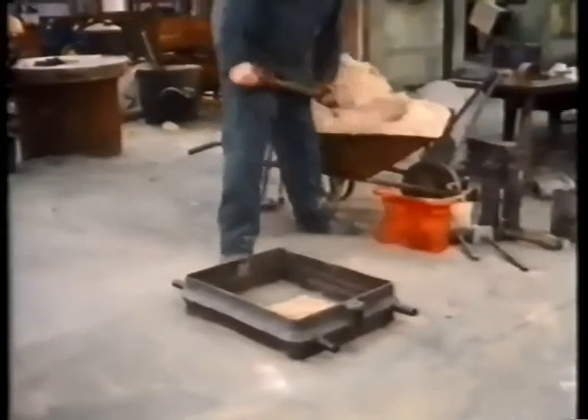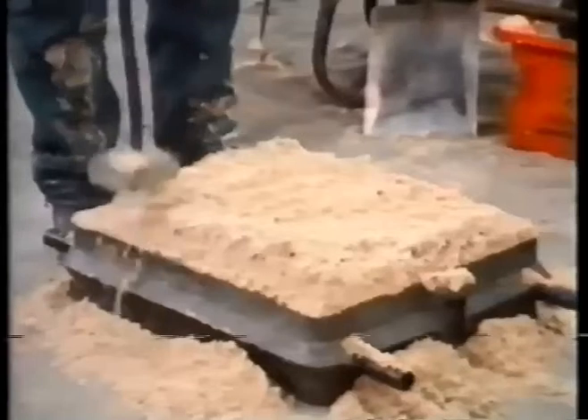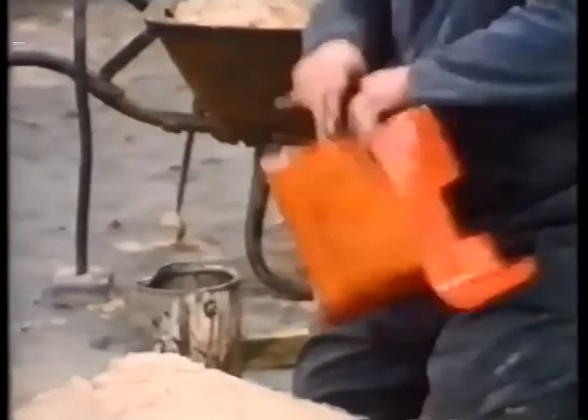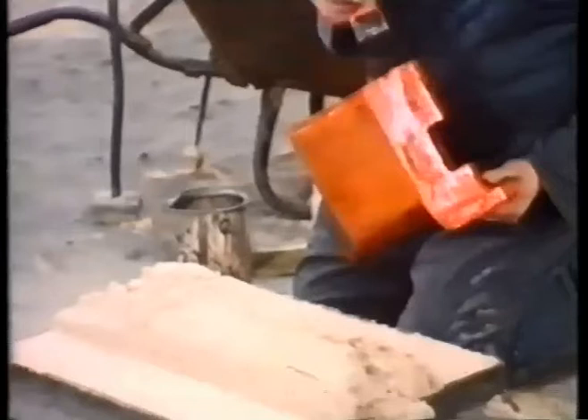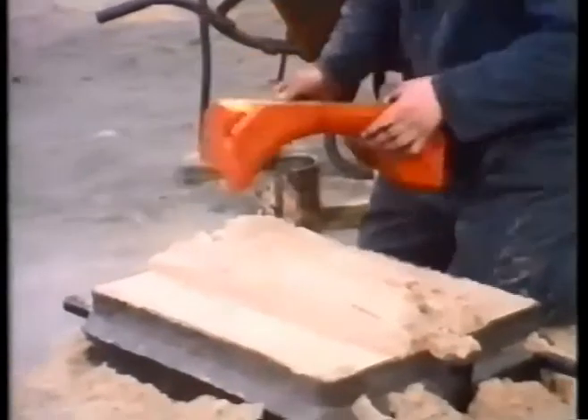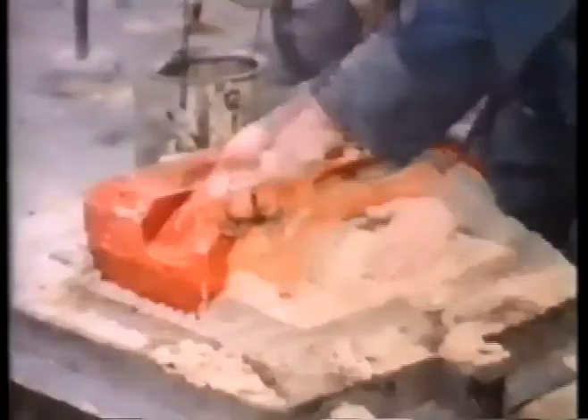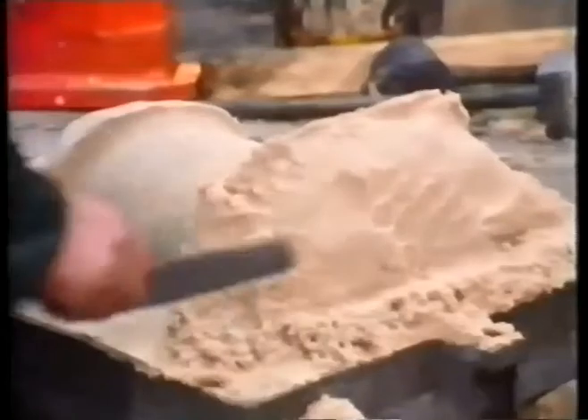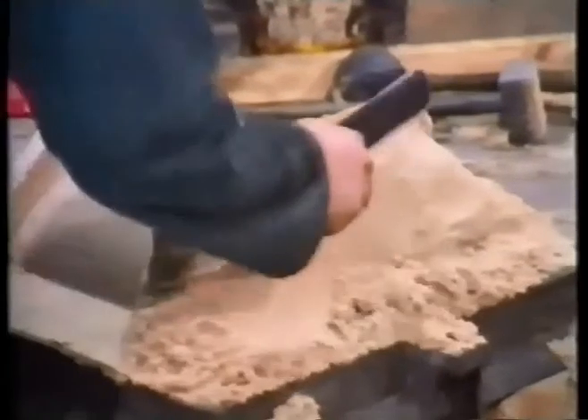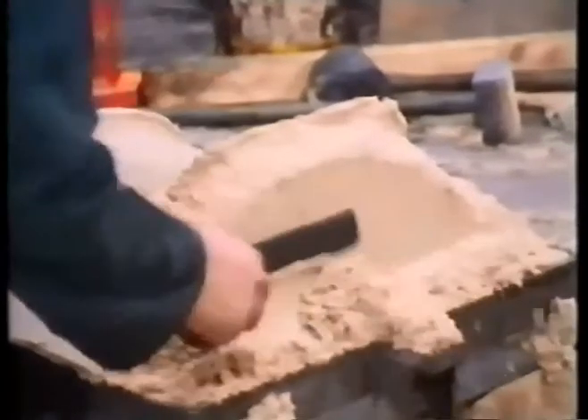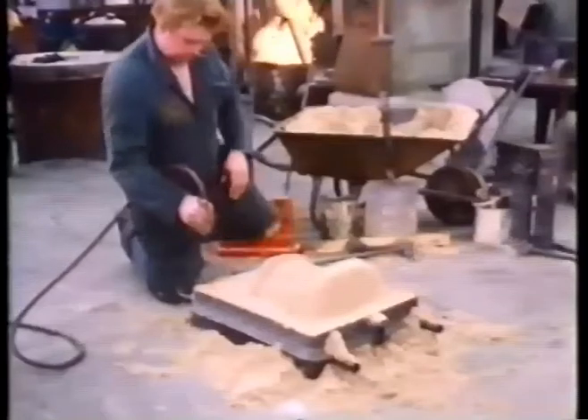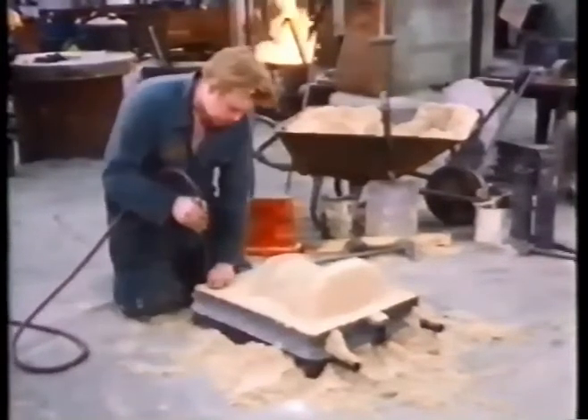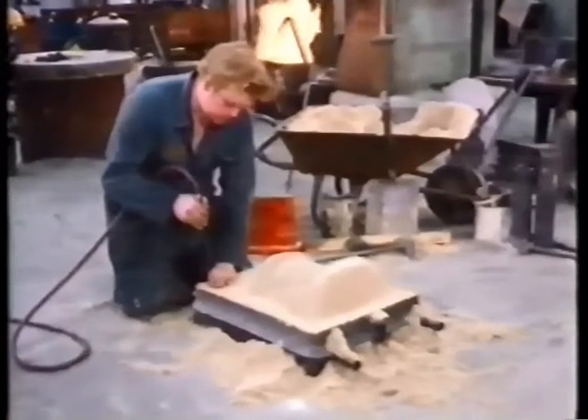First, a mould box is filled with a suitable foundry sand, which is tamped down to ensure that it fills the box properly. Then a wooden pattern of the shape of the bearing we require is placed onto the sand to form the running surface of the final bearing. The bottom half is then trimmed and hardened by passing carbon dioxide gas into the sand, which contains water glass as the hardening agent.